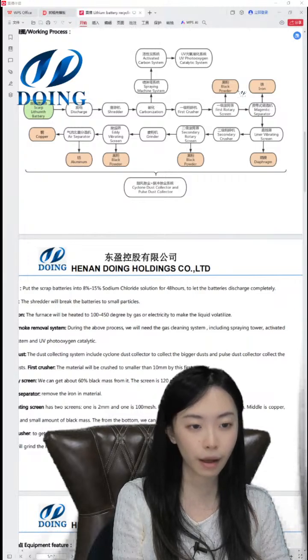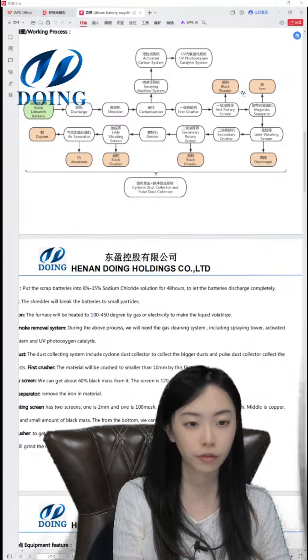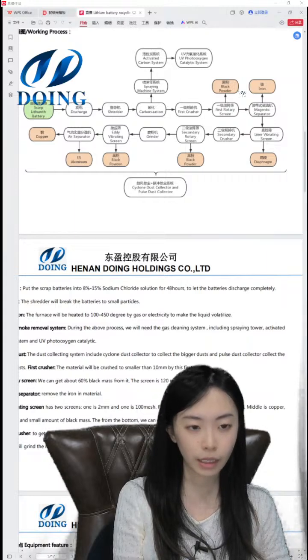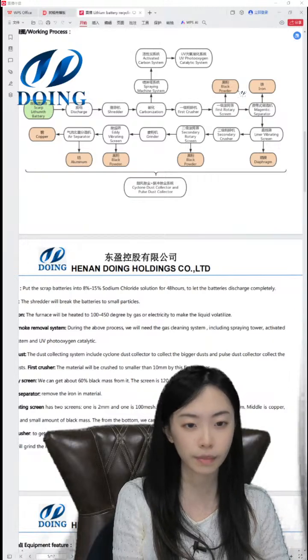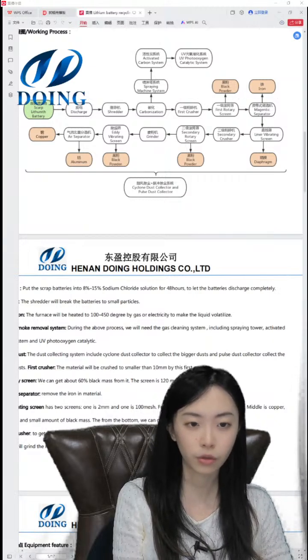It uses the combined action of the airflow and the vibrating friction on the material. So the large copper particles will settle at the bottom, and the smaller aluminium particles are suspended on the surface of the raw material layer by the action of the airflow. By this link, the recovery rate of the copper and aluminium is about 98%. Here is the whole process of the lithium battery recycling machine.